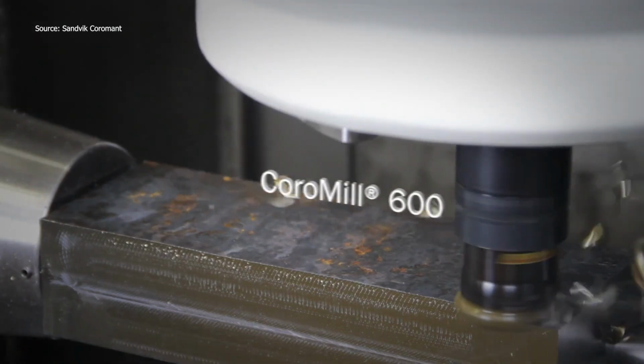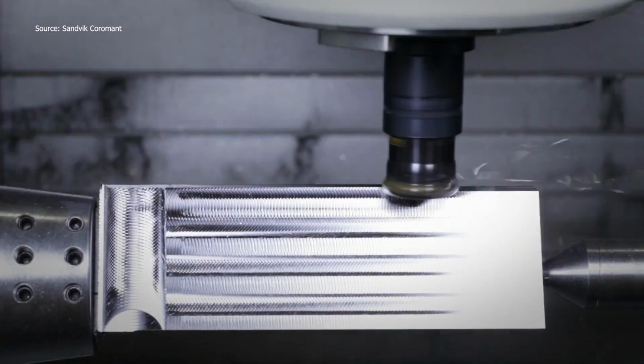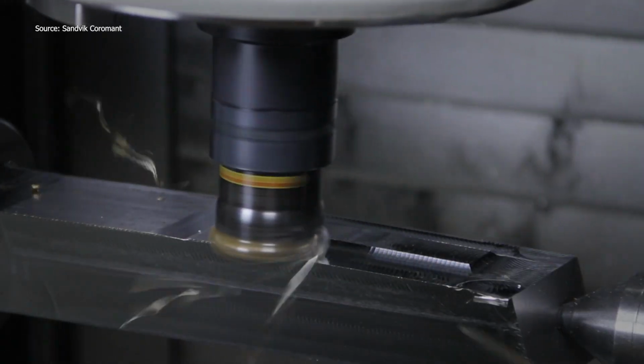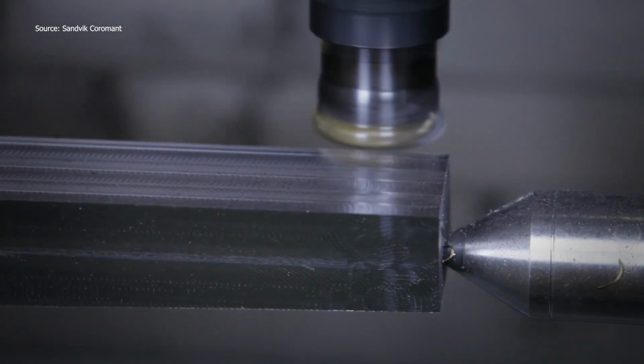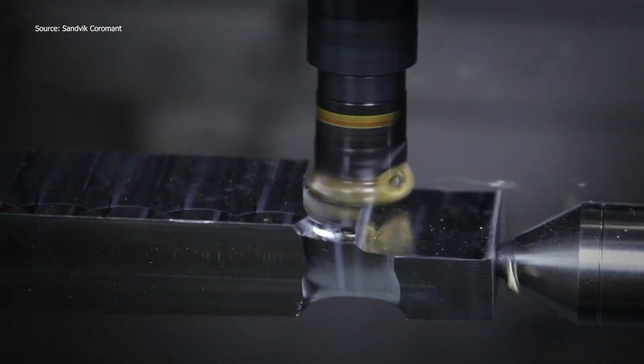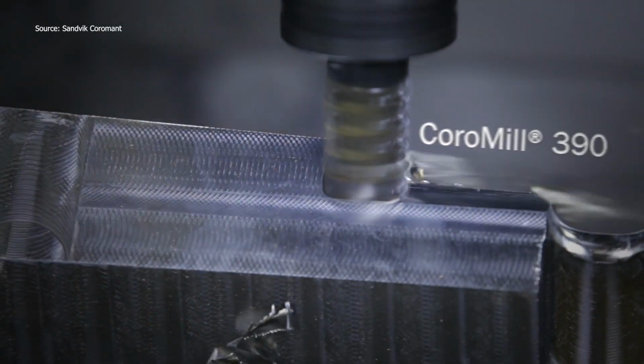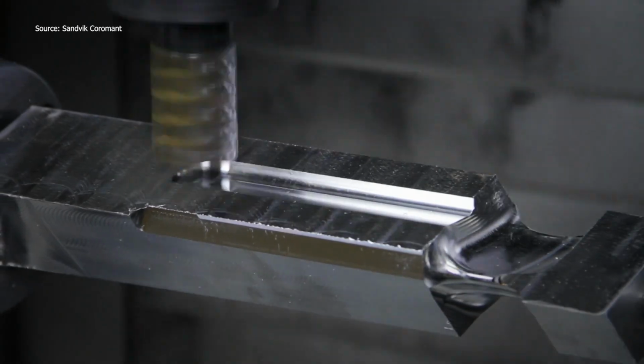Blade production for turbines involves both roughing and finishing on 4 or 5-axis CNC machines. Materials, such as nickel-based alloys, are machined at cutting speeds between 40 and 80 meters per minute with carbide tools and up to 400 meters per minute using ceramics. Feed per tooth ranges from 0.1 to 0.5 millimeters, and depth of cut may reach 15% of the insert diameter.